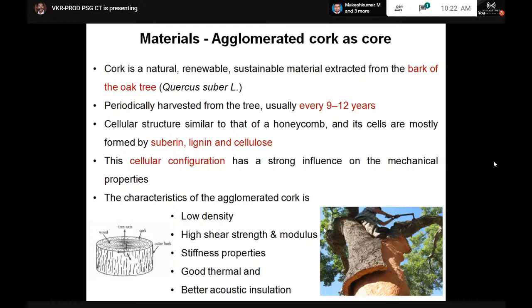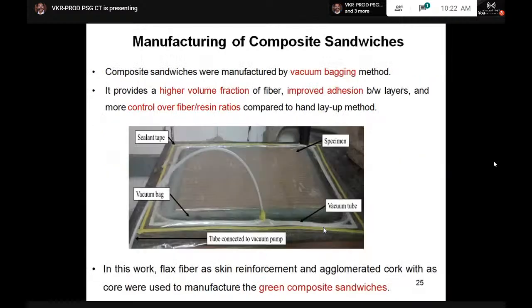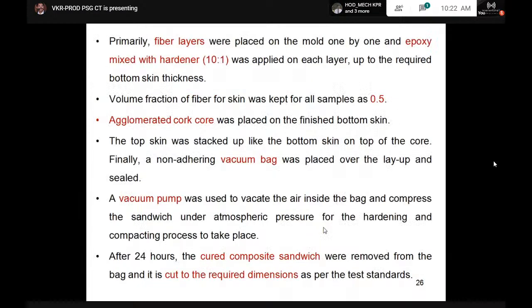So more or less we used natural material except a small amount of resin which is used for binding the skin to the core. Of course, we produced this in a vacuum packing technique, and this was cured at room temperature. We didn't go for oven curing. There is an option we can think about. We can go for oven curing instead of autoclave curing. Autoclave is expensive, but of course, oven can be a cheap solution.